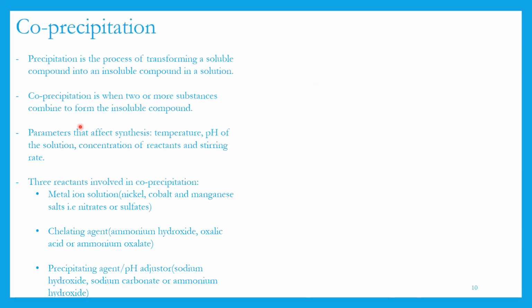And so, as I mentioned before, parameters that affect the synthesis are the temperature, the pH of the solution, which is really important, the concentration of the reactants, and then the stirring rate. If you're using a continuous stirred reactor, the stirring rate affects the morphology of the final material. And the three main reactants involved in this co-precipitation process, we have the metal ions, so the nickel, cobalt, manganese.